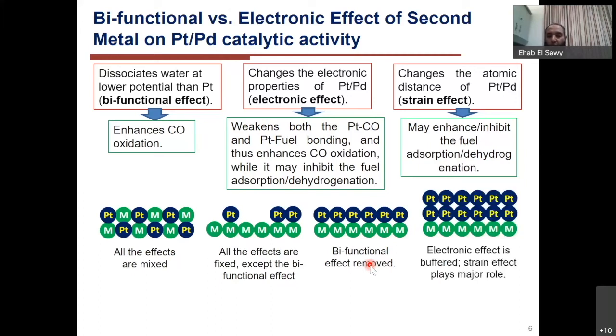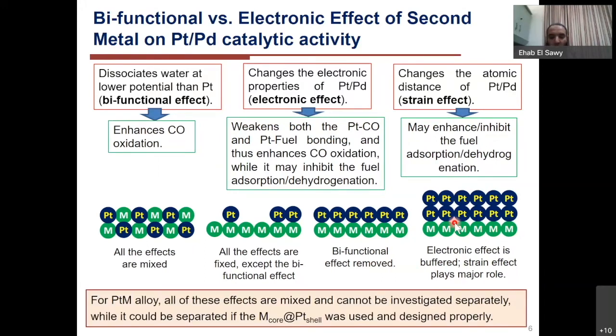And further, if we start to add more than one monolayer, in this case we are buffering the electronic effect that's coming from the core electrons to the outermost active surface, and therefore by changing only the core size, we could control the strain effect. So I hope that I convinced you that all these effects will be mixed in an alloy. However, when we have a core shell structure with controlled coverage, we will be able to distinguish between these effects.